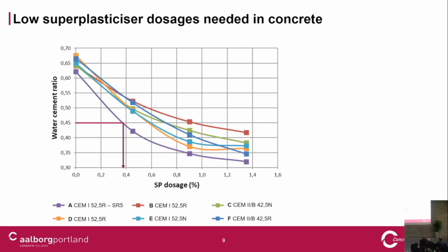Just to compare - let's say we need a concrete with 0.45 water-cement ratio and a specific flow. Then we should use around 0.4% superplasticizer with the cement from Aalborg.